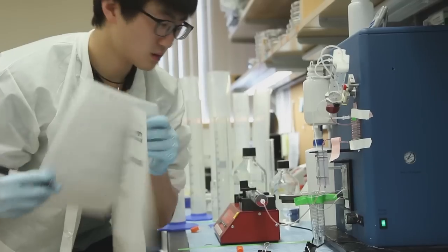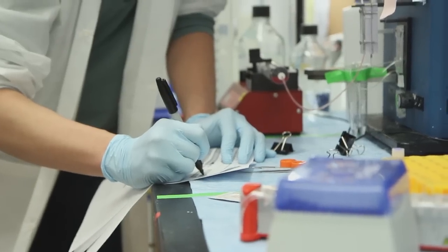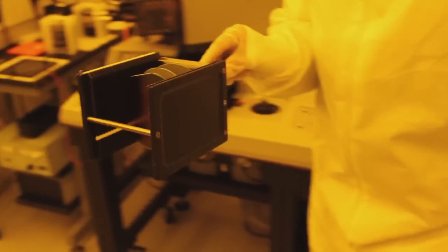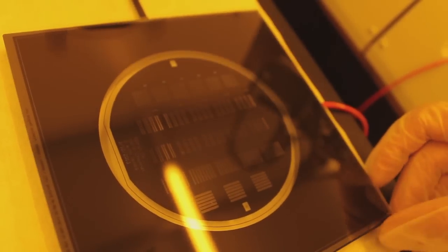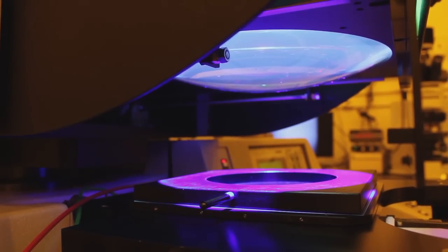The process may begin with an idea, an observation, or a combination of the two, then progress from a CAD-CAM design to our clean room for microfabrication. We start out with just a silicon wafer — a very flat surface. On top of it we spread a very thin layer of plastic material that's sensitive to UV light, then expose that material to light through a mask we've drawn. The parts exposed to light, where we want our channels, harden, and then we dissolve away everything else.